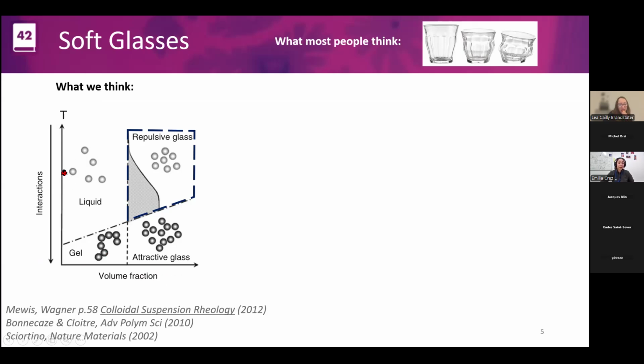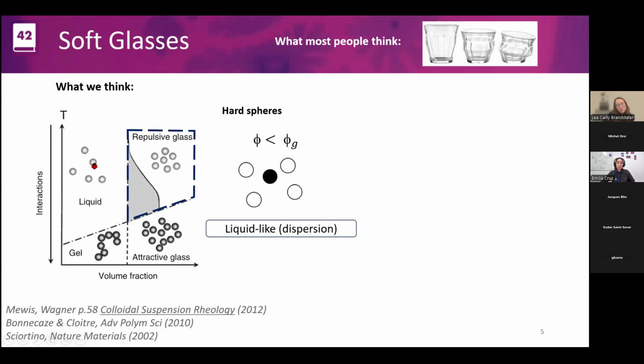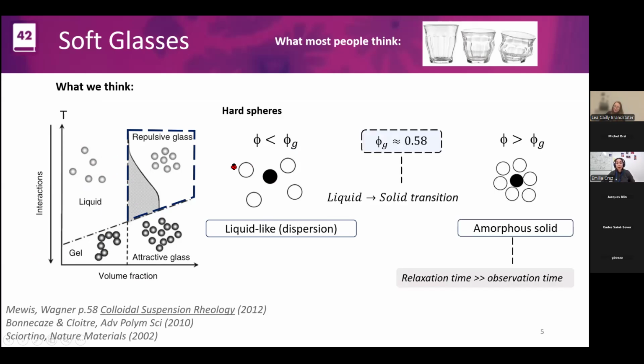But let's focus now on just a dispersion of hard spheres in a liquid. So no interaction is involved. We're going to be in this region of that phase diagram to prepare the soft glass, and I will show you how that works. So you have this colloid swimming in the solvent. It's a liquid-like dispersion. We have chosen colloidal hard spheres. They can be moving around because of Brownian motion, for example. But then you start putting more and more particles, and there will be a phase transition at some point, because at some point you put so many particles that you have a liquid to solid transition, and it's very sharp, it's very clear.